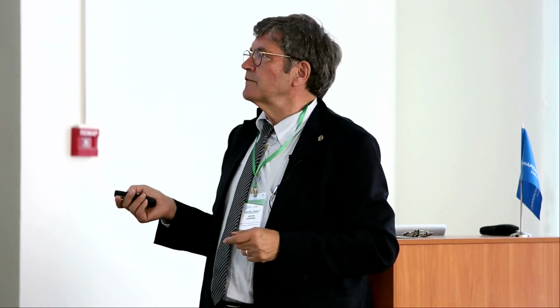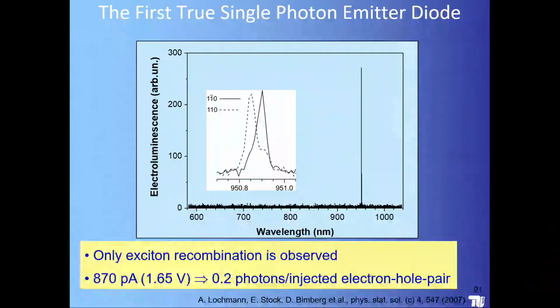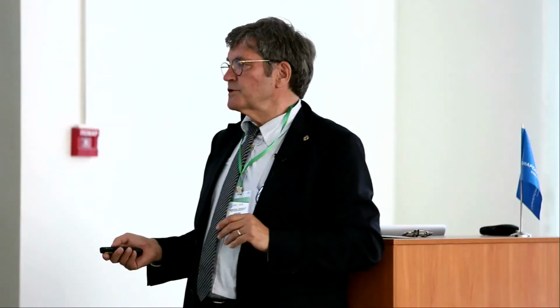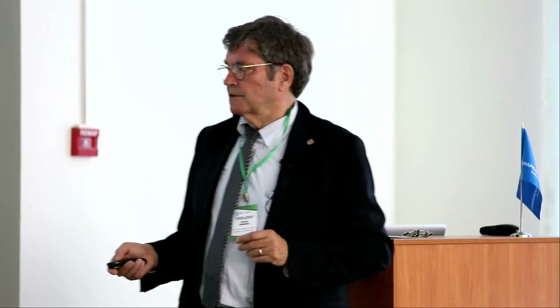And here is the result: a completely empty spectrum, completely empty, weak pumping. You see a recombination of one single exciton inside. That is, what you see here is a qubit. And if you look a little more in detail with a high resolution spectrometer, you see that indeed, as predicted by our theoretical calculations, the light emission is polarized. Half of it is along 1-1-0 and the other half along 1-minus-1-0, the fundamental axes of the 3-5 semiconductor. And the efficiency already was pretty good: about 20% of photons per injected electron-hole pair.